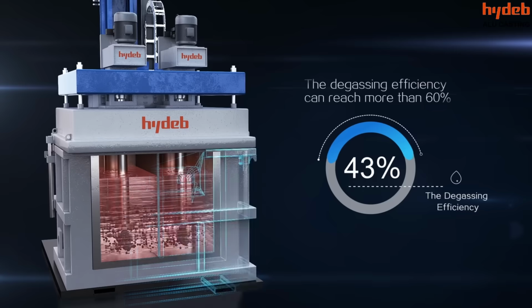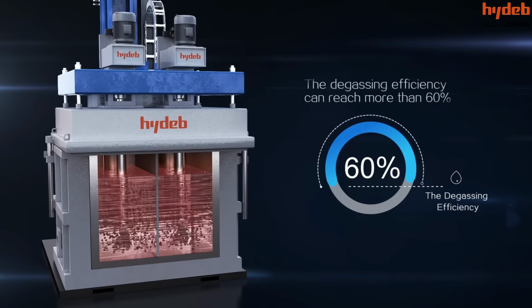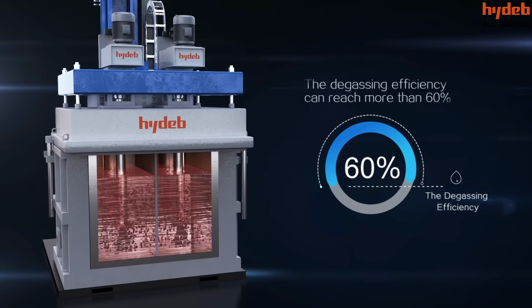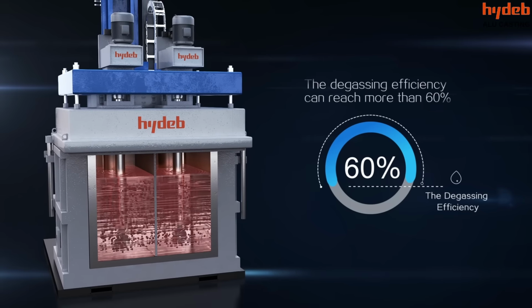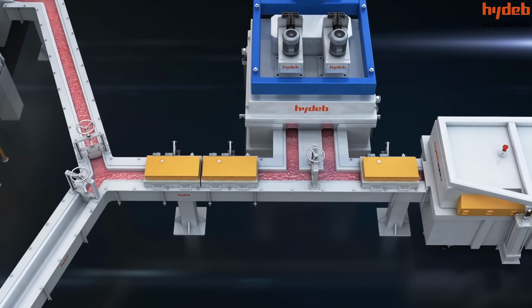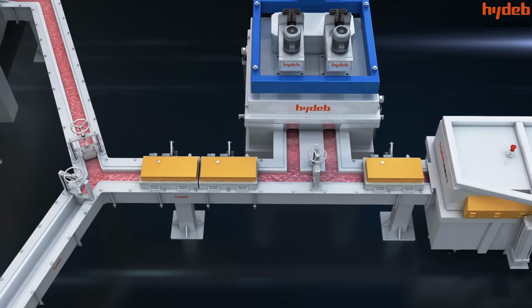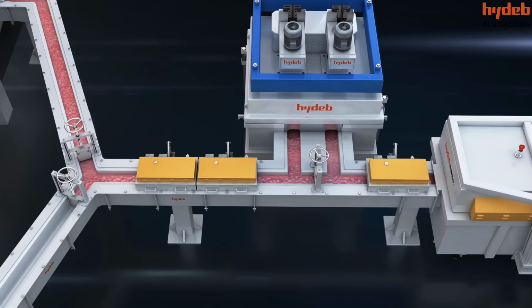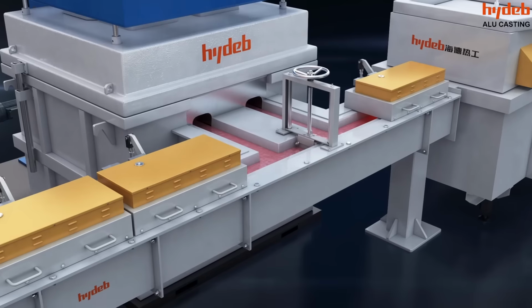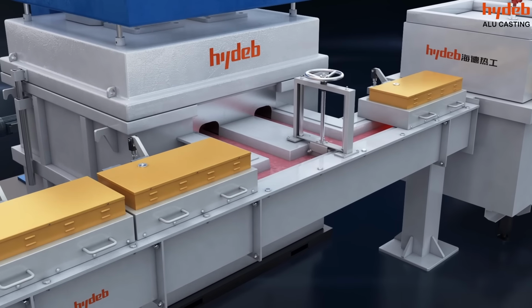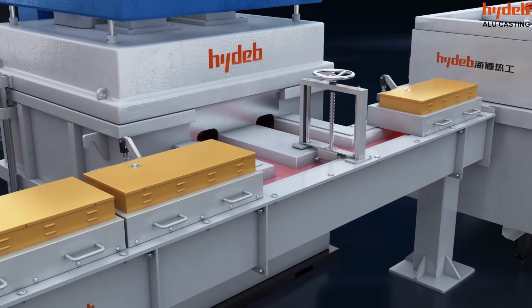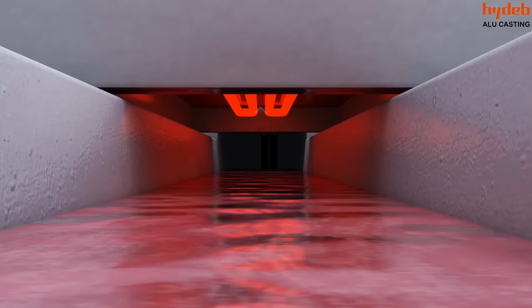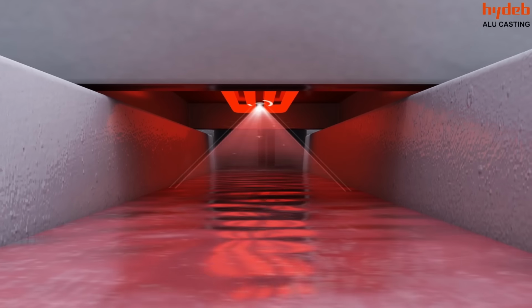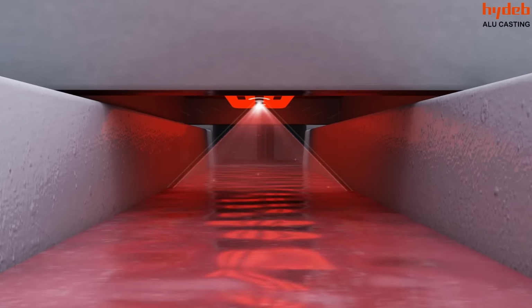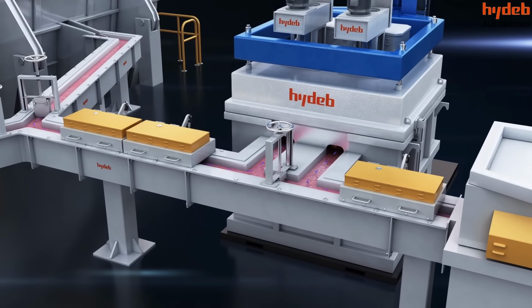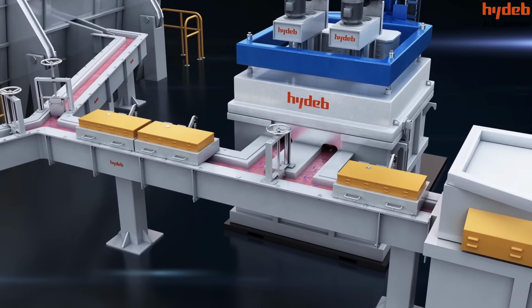Mixed with chlorine refining, the unit can reduce the content of alkali metals in the flux to less than 2 ppm after refining. Molten aluminum transfer launder has no infiltration with the molten aluminum, with low thermal conductivity and high strength. The heat loss can be reduced by more than 50% by adding the cover of the distributor, and also adding the heating device of the distributor can keep the temperature drop of the molten aluminum to a minimum, thus reducing its temperature when it comes out of the furnace.